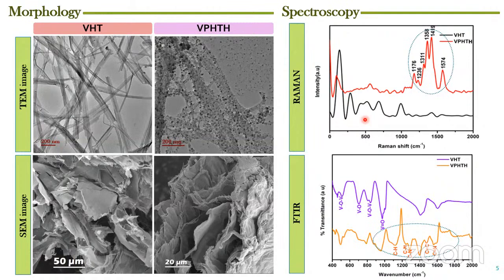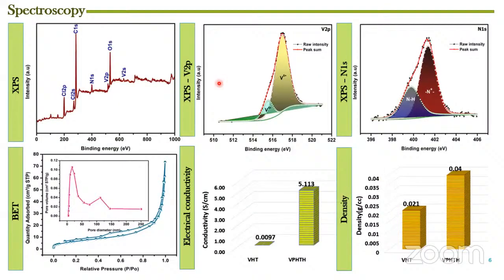The SEM image shows a highly porous and layered structure, which is highly beneficial for absorption-dominant shielding, because the vast surface area provided by this porous and layered structure helps multiple internal reflections and scattering, due to which these EM waves get dissipated. Spectroscopic analysis like Raman, FTIR, and XPS confirms the presence of polymerization. BET isotherm was studied to examine the porosity and surface area, and the surface area of the composite sample was improved by 3 times compared to the pristine sample.